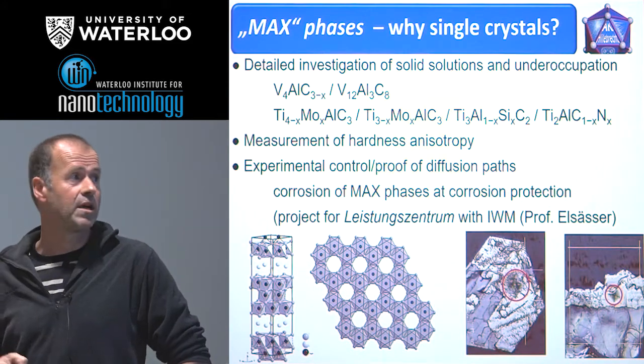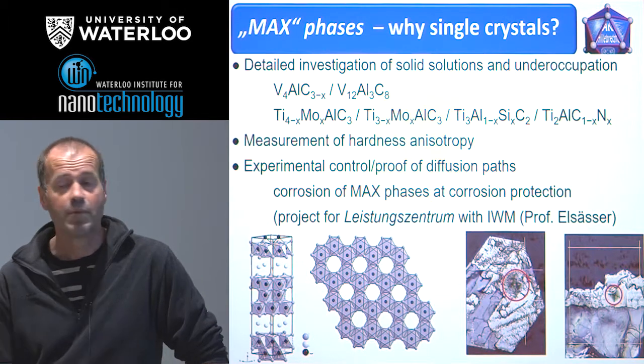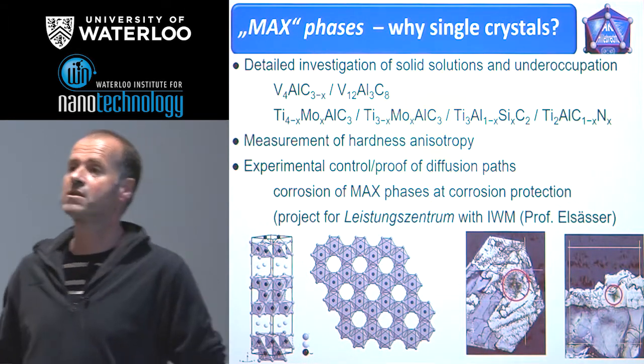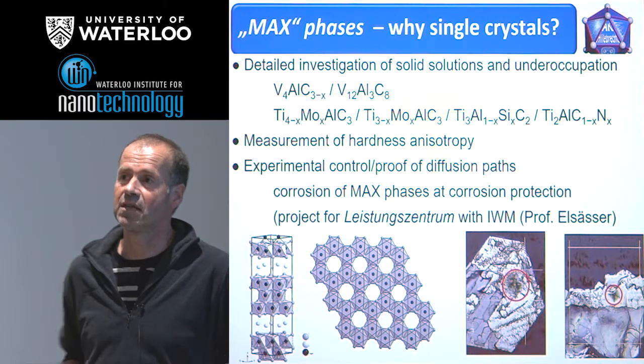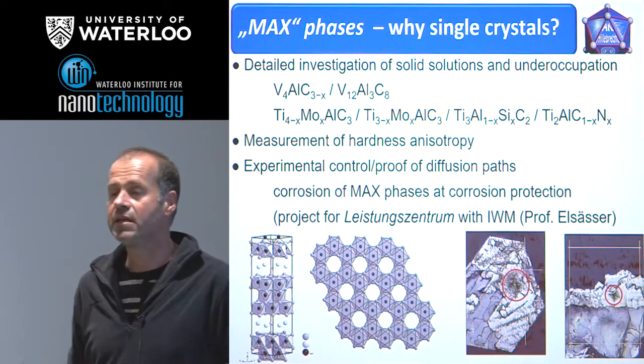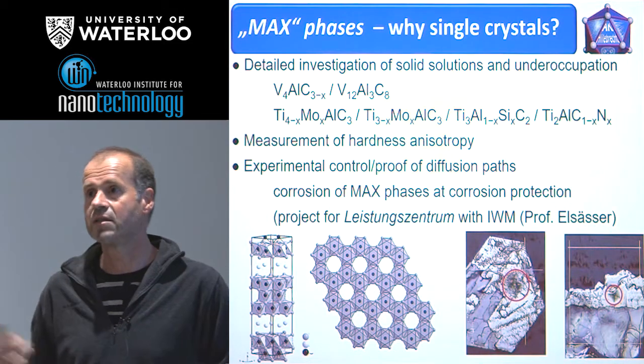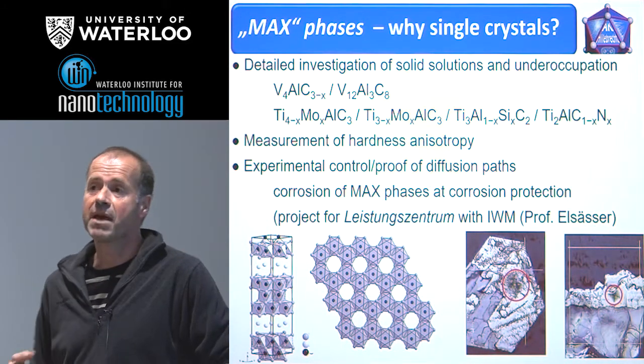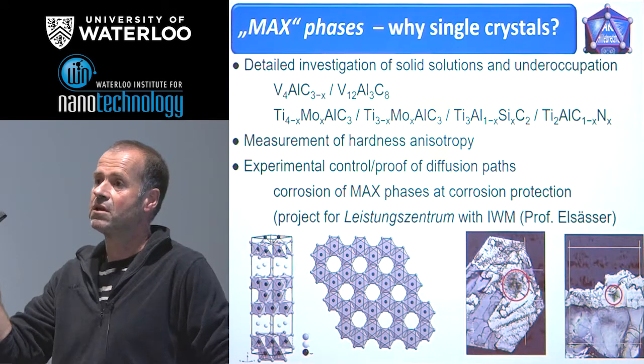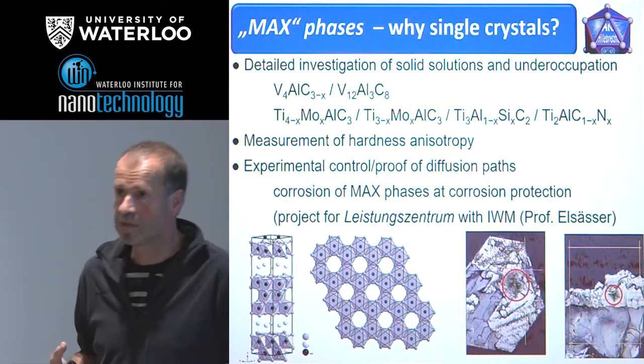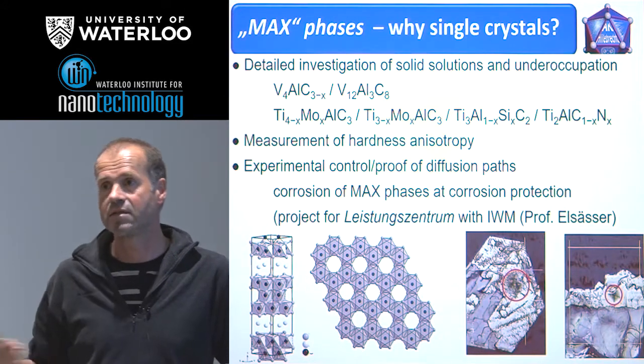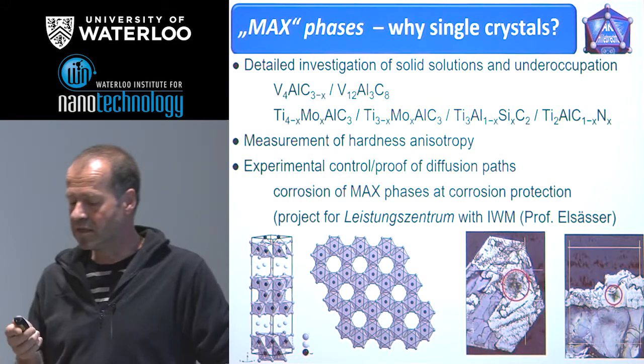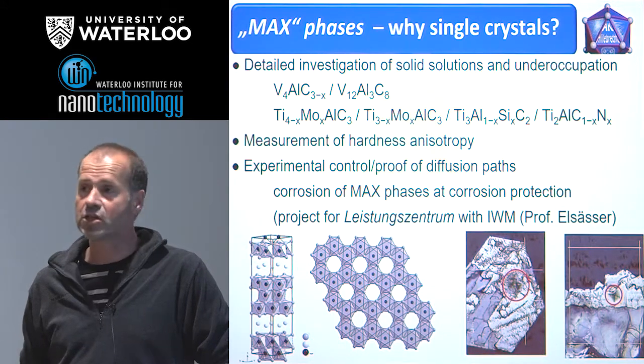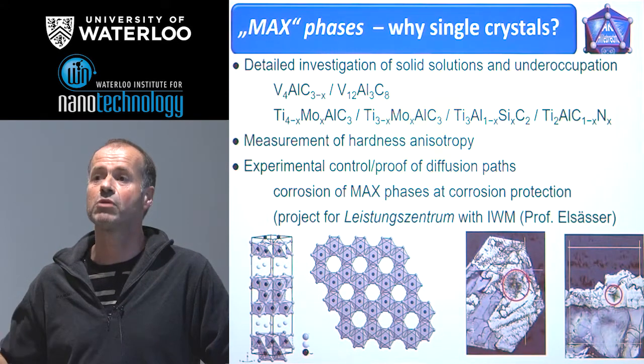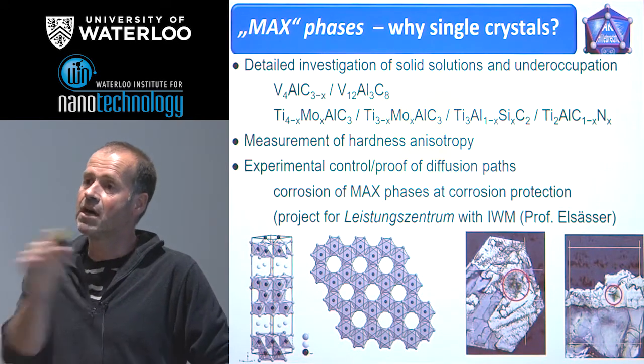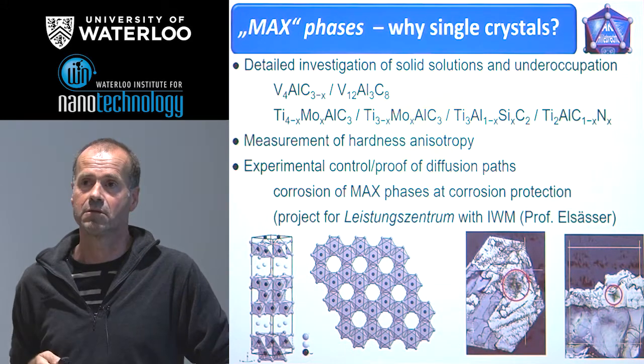And another project we had in Freiburg was the question of corrosion, because if you try to use these ternary carbides for protection, lots of intermetallics are attacked by saline, by oxygen conditions or oxidizing conditions, and then you may use these MAX phases as a layer for the protection. And now you have transport properties, for example, ions or what else were taken in or out, and so we had the idea to measure or to control these diffusion processes on the basis of single crystals, how the ions migrate in or out. That was a nice idea.